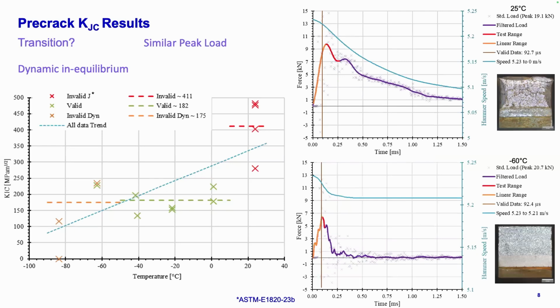I've picked out one of my pre-crack samples that was ductile and was brittle. As we can see, again, very classical brittle and ductile behavior. We come up to a load and snap right off from the brittle behavior, very nice. And then we're coming up and having some plasticity coming through. The little jump during the plastic region is very typical for plastic collapse, something that is very difficult to work on when we have small samples.